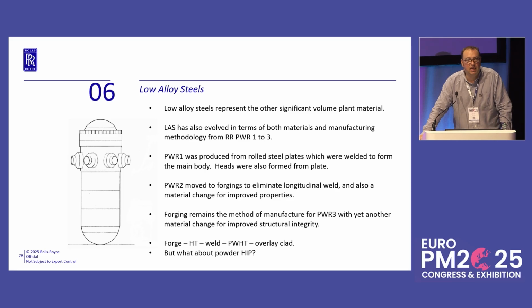So over the decades and over the plants, we have used low alloy steels for our major vessels, and they represent a significant volume of the large forgings that we do. And we've evolved over the plants in terms of both the materials and the manufacturing method. So we're at the point today where we have large cylindrical forgings, which again allows us to remove welds, that we basically make in sections up at Sheffield Forgemasters, which then come down to Derby, where we assemble and clad.